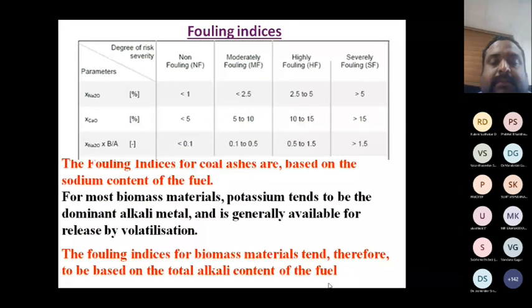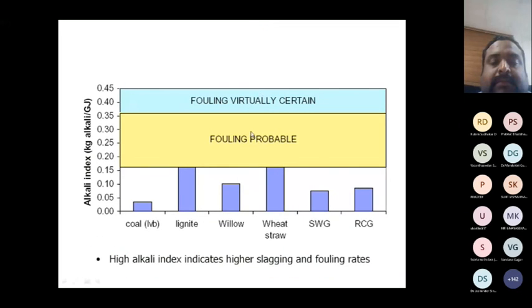In the case of fouling indices, again this is available for coal. Based on sodium, it is non-fouling if low, moderately fouling if less than 2.5%, and highly fouling at 2.5 to 5% sodium. The fouling indexes for coal ashes are based on the sodium content of the fuel because sodium is most available. Whereas in biomass, potassium is potentially available. For most biomass materials, potassium tends to be the dominant alkali metal and is generally released, and it is also partly volatile. So fouling indexes of biomass materials have to be based on total alkali. Don't go for such classification; instead, go for the total alkali content of the fuel. These are all the classifications: fouling probable, fouling virtually certain, based on the alkali index.